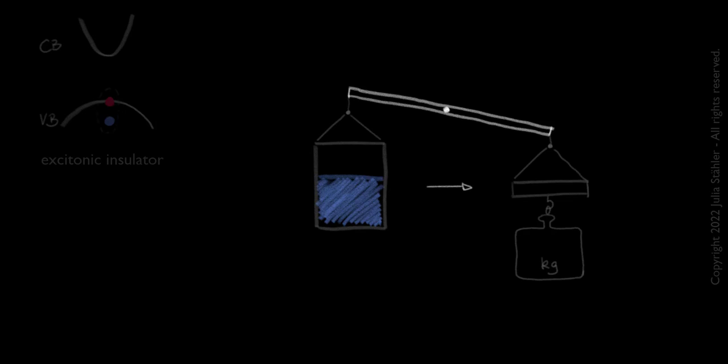with all available electrons. Now, electrons are of course no water drops, and quantum effects like tunneling can occur in such a system. Electrons leave the reservoir and become part of the exciton condensate until the free energy is minimized and equilibrium is reached. The excitonic insulator is stabilized.